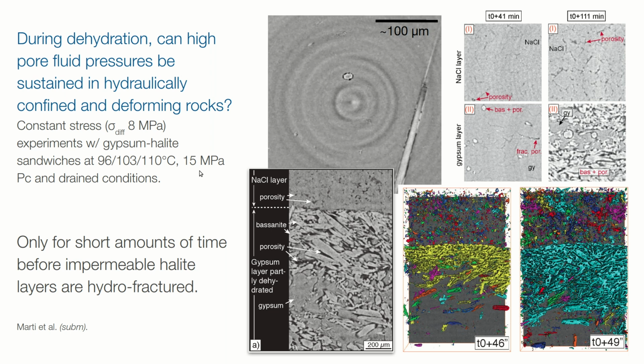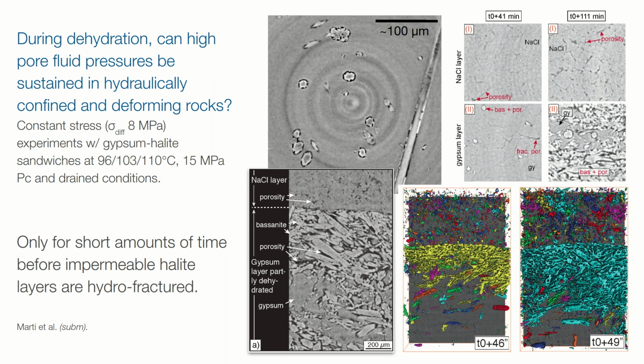We did find that, by the way, these fluid overpressures could only be supported for very short amounts of time before the water hydrofractured its way through the halite, and this is something you can see here. These are images from a central gypsum layer in the sample and an adjacent halite layer here at different points in time, and you can quite clearly see that there is nice porosity forming in here, which goes along with the reaction of the gypsum, and this is a rendering of the same pretty much in 3D. All of that happens over a very short time scale.